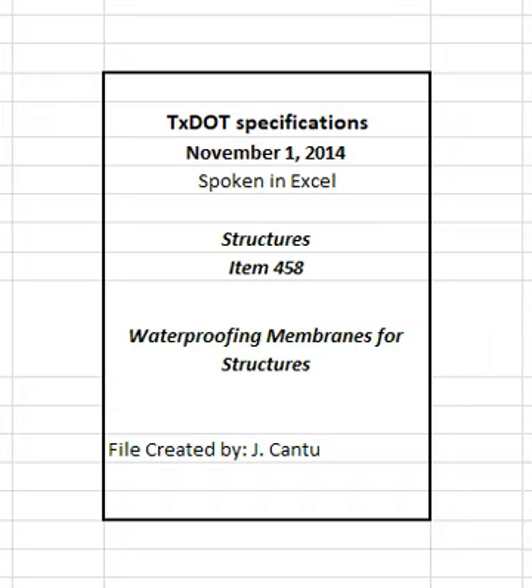Provide a minimum thickness of protection of 1 inches, consisting of asphalt plank or asphalt mat unless otherwise specified on the plans. Coat the edges and ends of adjacent planks already laid with cold asphalt emulsion as successive planks are laid. Lay the planks tightly against those previously laid so the emulsion will completely fill the joints and be squeezed out the top. Fill any joints not completely full after planks have been laid with emulsion.